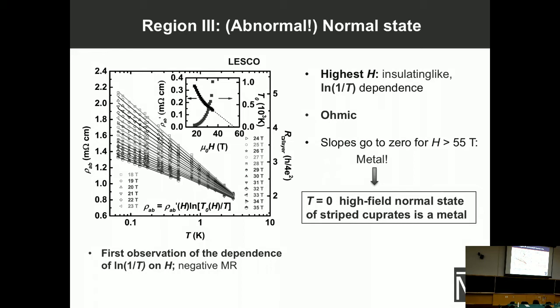And the same result is found in other materials. So this data suggests that the high field ground state of these striped cuprates is a metal, which is different from the underdoped LSCO, where the data suggests insulating behavior. So of course, we still don't understand why this is logarithmic, and don't understand the properties of this state, and this is also an open question, what happens at higher fields. So this will all have to be the subject of some further studies.